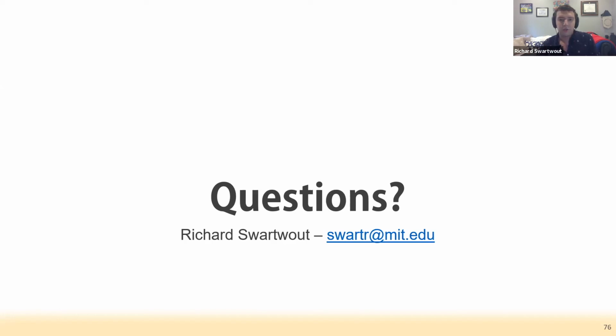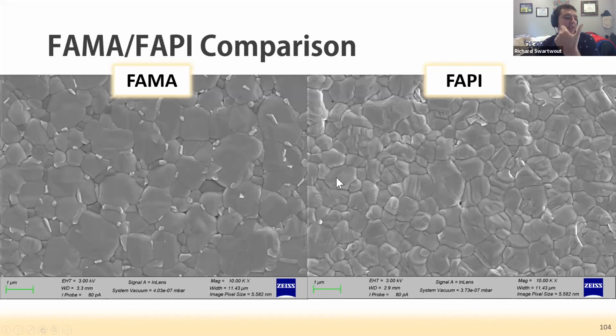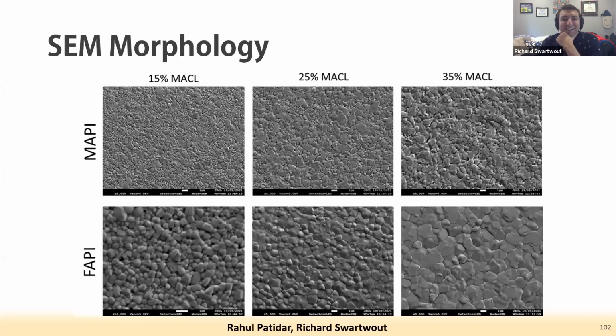I can show you as well, I have a ton of backup slides. For the recrystallized films, just as a comparison - these are actually not even the best films I've had, but they compare pretty equally to a traditional formamidinium lead iodide film done by DMF-based anti-solvent routes, with grain sizes around a micron. Rahul did a nice study, so I stole his image for this - thank you, Rahul - of doing methylammonium chloride additives, and we see grain growth again in this recrystallization technique. It's a little hard to see, but the scale bar here is also a micron. So these are in the field, relatively large grain sizes.